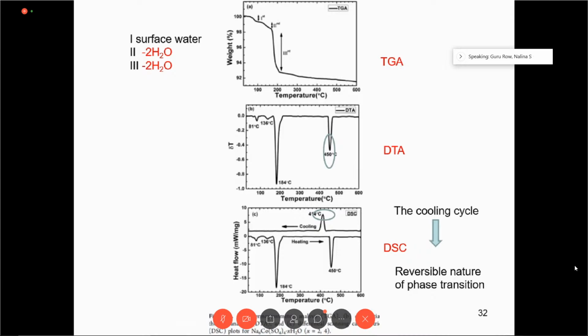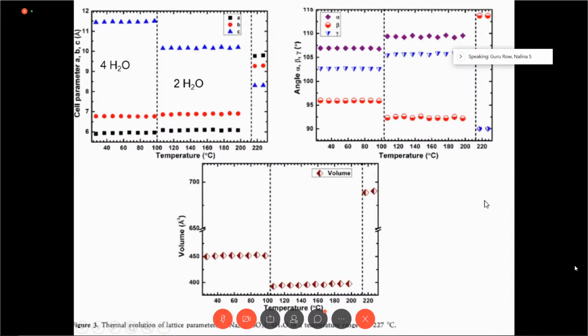thermogravimetric analysis. So when we take the compound and heat it up, it loses the so-called surface water, referred to as the first transition stage, where the crystals have some amount of moisture condensed on them. And once that goes away, the second stage is the temperature at which the 2 water molecules go. So the compound essentially converts from 4H2O completely to 2H2O. So we can study the structures of these compounds at 2H2O and 4H2O.